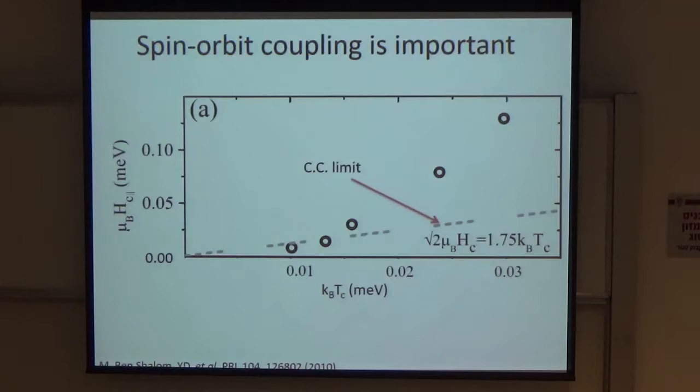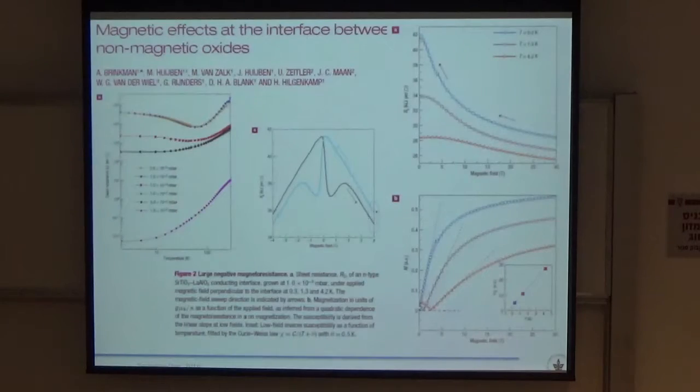If we have strong spin-orbit interaction, this condition is relaxed, or if it's not S-wave. Okay, but it's 300 mK, so probably it's an S-wave superconductor, and now we have a strong spin-orbit interaction, and spin-orbit interaction changes with electric field, which is also very nice. So we have a tunable spin-orbit, which is about 3 milli-electron volts, of the order of the Fermi energy, which makes it also an interesting system for spintronics applications.